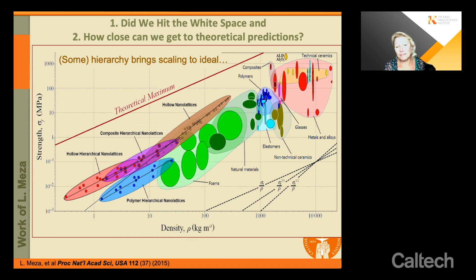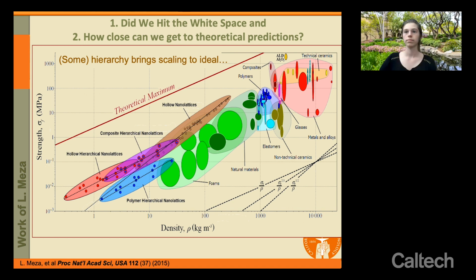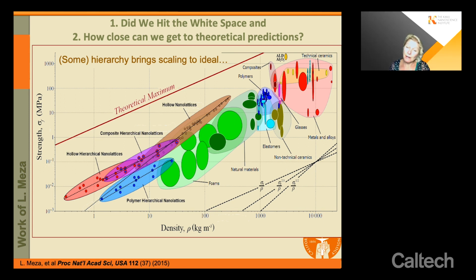And so this is where the fatigue comes from. Even though they fully recover globally, there is still some damage initiation at the nodes. It is entirely possible, and we've actually observed it, that in some configurations there are micro cracks and nano cracks that form at these nodes, and then they just open and close under fatigue loading conditions. So they don't affect the recovery, but they do deteriorate the strength. And this is why our strength here falls off at a higher rate than what is theoretically predicted.